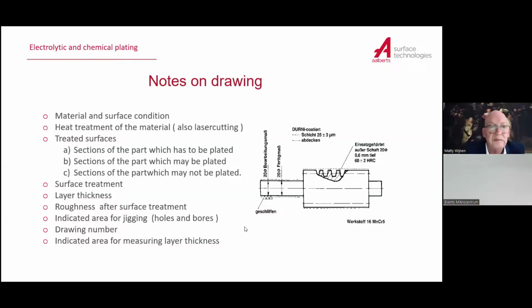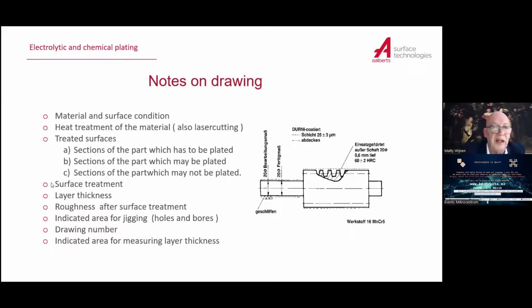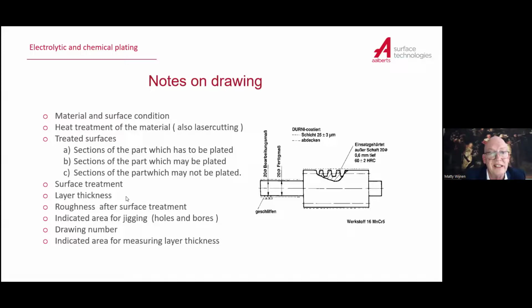Okay. So surface treatment is, of course, necessary. The layer thickness. And a question is coming in very quickly: are the dimensions inclusive of the nickel layer thickness? Normally not. The layer thickness is always added onto the dimensions on the drawing, or it has to be noted as dimensions count after plating.